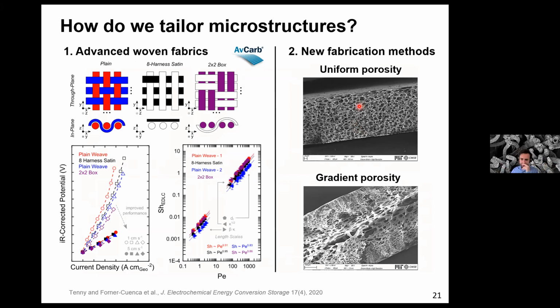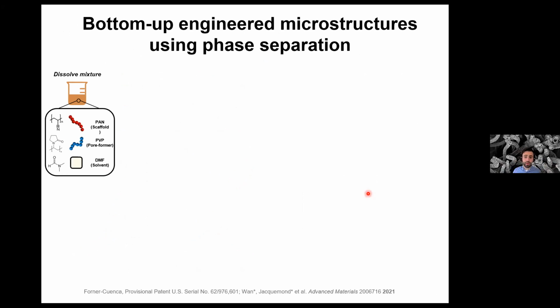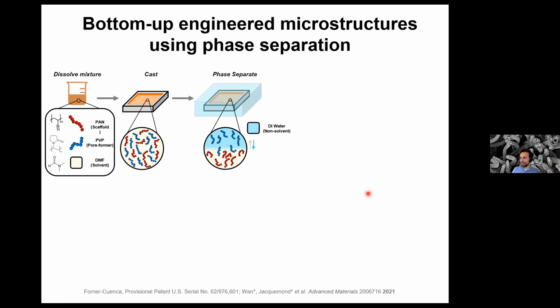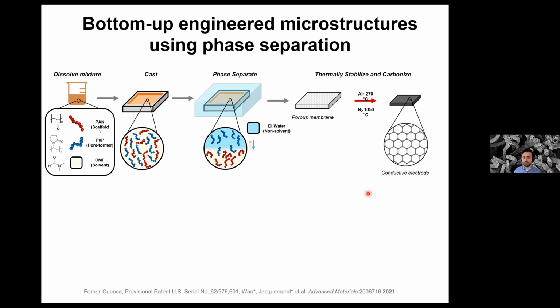So anyway, the last thing that I have is that we are now developing our own scaffold, so our own 3D structures for use in flow batteries, but also for use in CO2 electrolyzers, for use in fuel cells. So we want to control from the bottom up the microstructure, and we want to be able to make structures that have either isoporous pore size distribution or porosity gradients, or bimodal or trimodal pore size distribution. And what we use is a technique that was developed for membrane materials, actually. So non-solvent induced phase separation is a very facile method in which you have a polymer solution, you cast it on a mold or on a glass plate, and then you immerse it in water to create the separation of the two phases. Ultimately, you get a porous membrane or a porous scaffold that you carbonize at high temperature to produce the conductive electrode.